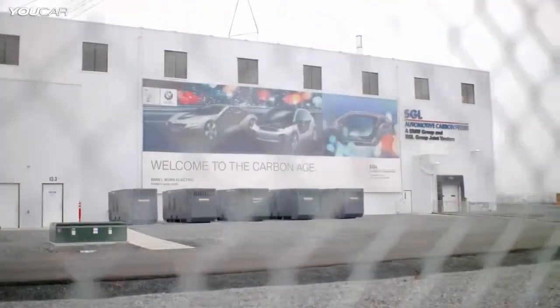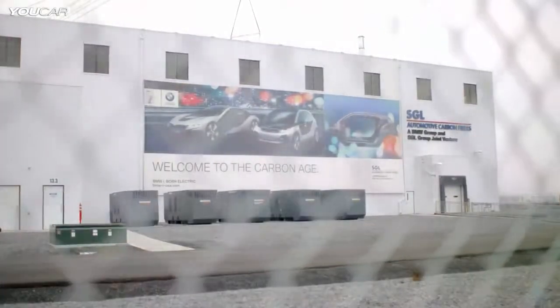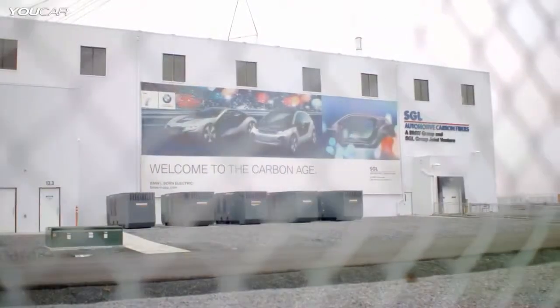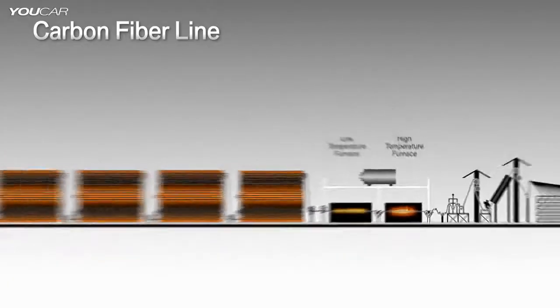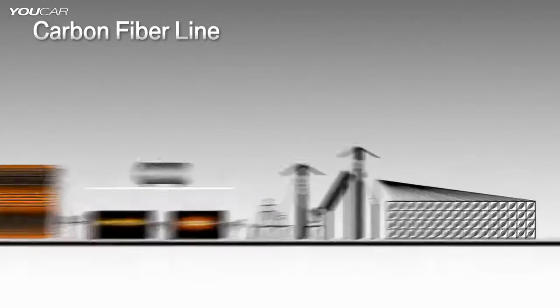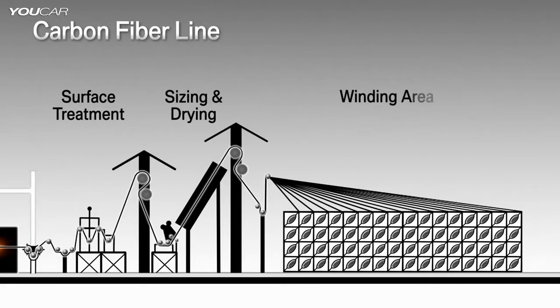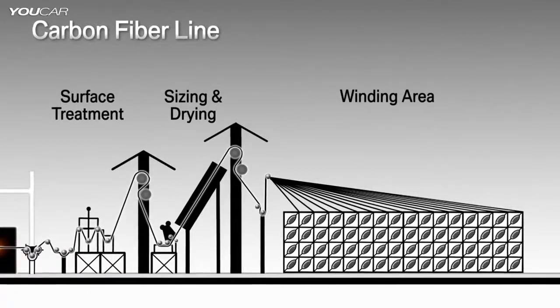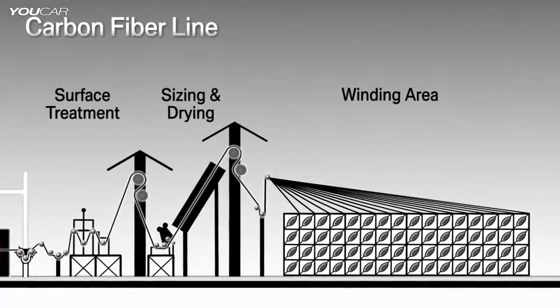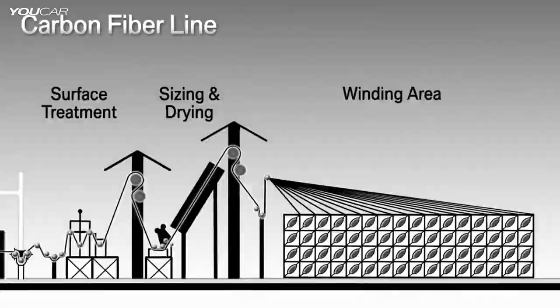Back to production. What happens to the fibers after carbonization is a manufacturing secret. The next step is the surface treatment. After carbonization, the material really has no functionality. It's sterile at this point. So in this process, we etch the outer skin of the material to allow it to bond with the resin system in later applications. After this, we size the material for usability and handleability. And we wind this material onto bobbins.